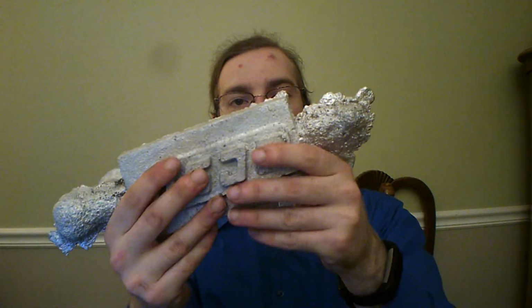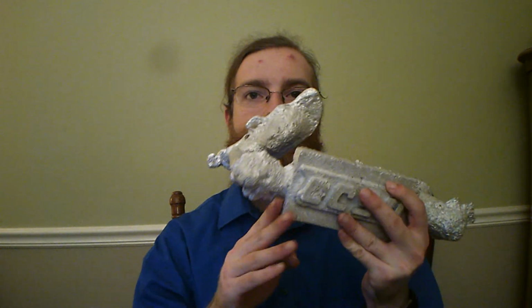Other flaws in both of these, to varying degrees, are here's a little bit of flashing. Flashing is when a little bit of metal gets in between the two halves at the parting line, where the cope and the drag separate. Same thing can be seen in the second one. Now in the real world, in order to make this a shippable product, I would have just stopped and redone this the second I pulled the pattern out with that going on, because that would take some milling to fix. All of these would be blended, the sprue and the riser would get hacked off, and that blended flush.